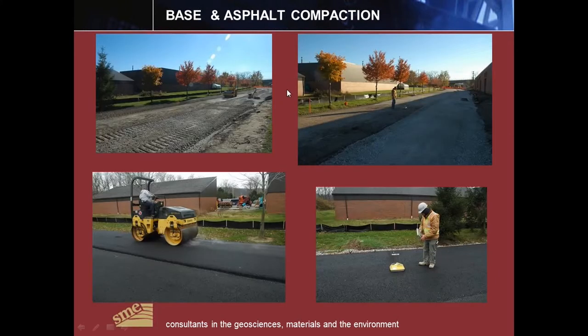In preparation for the road bed, the railroad ties and rails were removed. The coarse ballast in the top of the pavement was stripped. The subgrade then was heavily proof rolled and then compacted with a vibratory drum roller. The proof roll was stable under the loaded aggregate trucks, but you'll see later that the compaction or density tests are lower than what you might expect.